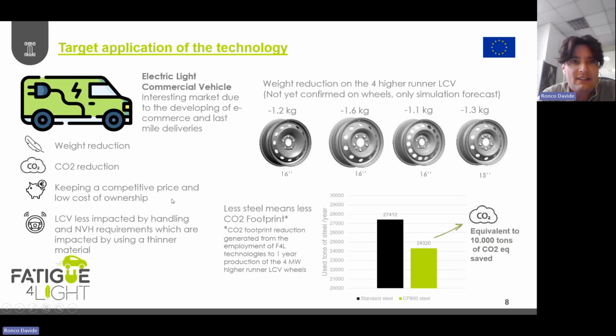Concluding, the target for this application, we identify this new material, new application on the wheel for the light commercial vehicle, because usually the light commercial vehicle has higher load and so higher thickness of disc and rim. With the CP800, we can reduce the weight, and so consequently also the CO2. We can keep a competitive price and low cost of ownership, and also the light commercial vehicle usually doesn't have particular requirements in terms of NVH or stiffness. So the comfort compared to the passenger car is a little bit less important, and this is the reason why we can decrease for that type of wheel the thickness of disc and rim.